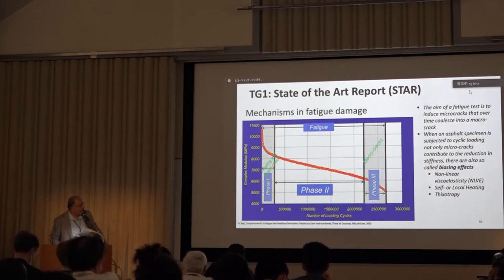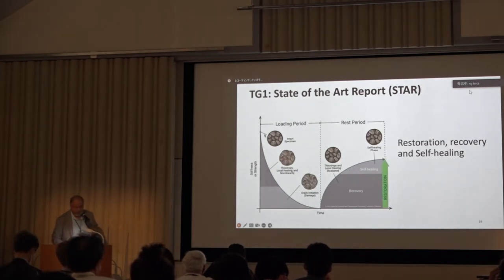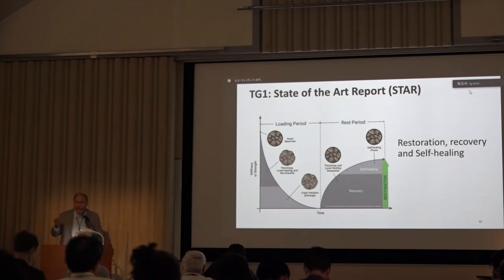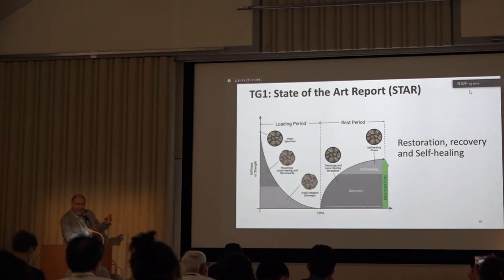What happens if we do a healing test, when we stop the loading, you can see that the property drops, we stop the loading, and then we have a recovery, or we call it here a restoration. A lot of people publish and say this is healing. Actually, it's not. It's like you take, I don't know, honey or ketchup, and you agitate it. It becomes more fluid, less viscous. But when you stop this agitation and leave it, it will go back and become semi-solid again. This is not healing. There was no damage, right? And this is what we need to differentiate.